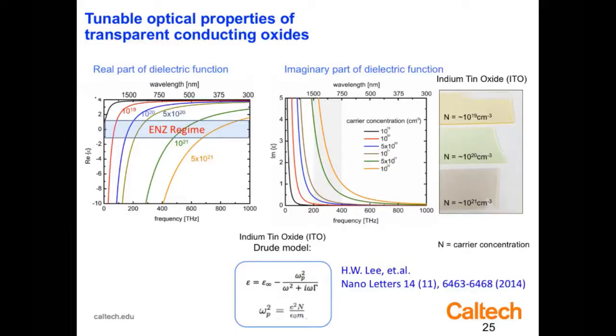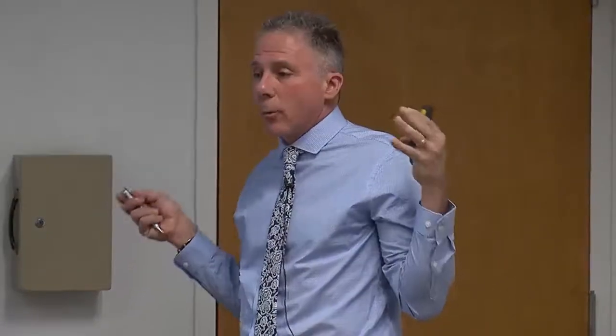And this is the imaginary part of the complex refractive index, or complex permittivity, of ITO, indium tin oxide. It's a wide band gap oxide that's degenerately doped, and that's how it gets its conductivity. And you can see its absorption is rising as the carrier density rises. And in fact, it starts to absorb in the visible. But if we look at the real part of the permittivity, we see here that from the infrared, the telecommunications band, into the near visible range, in this carrier density range, where the carrier density goes from 10^19 to about 10^21, we can shift the permittivity from positive to negative. That literally means, in electromagnetic terms, we're changing the material from being dielectric to metallic.